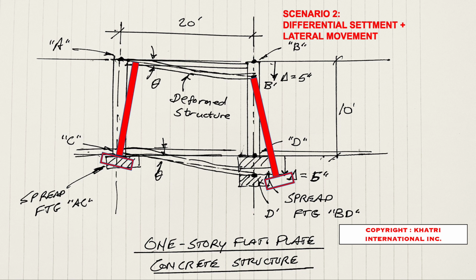And remember that none of these loads, which are the uneven settlement loads, are accounted for in our design process. We don't design for uneven settlement. It's not a criteria that we consider. We also don't design for a fatigue life or a corrosion life on the rebar. We assume that the concrete is going to protect that rebar. As you can see, in a saltwater environment, when you're close to the ocean, you need more protection.